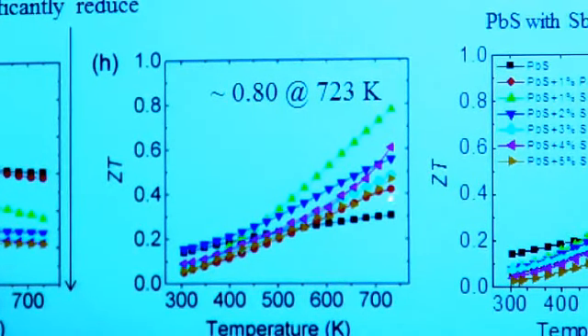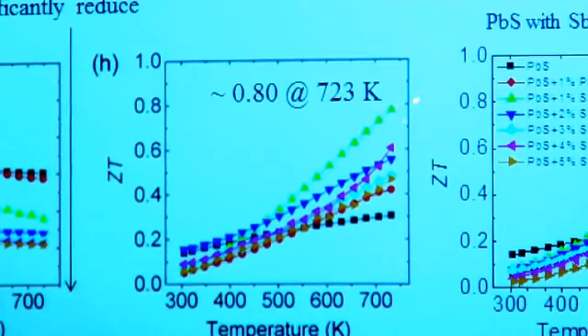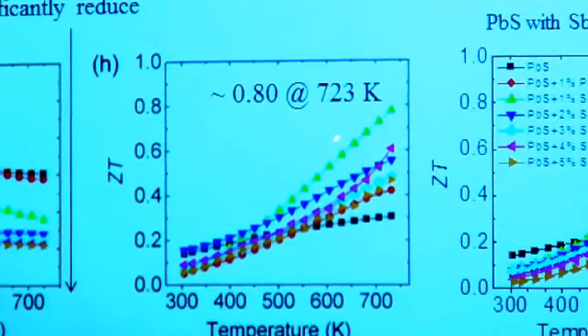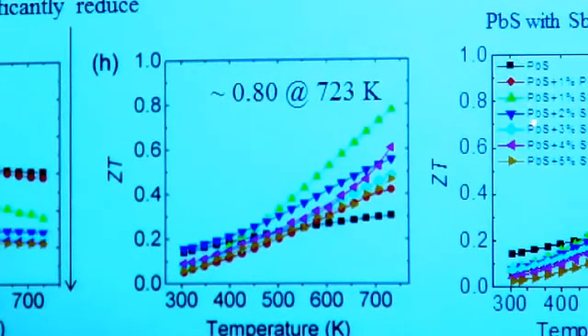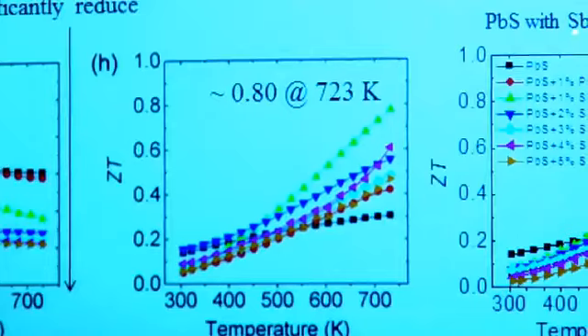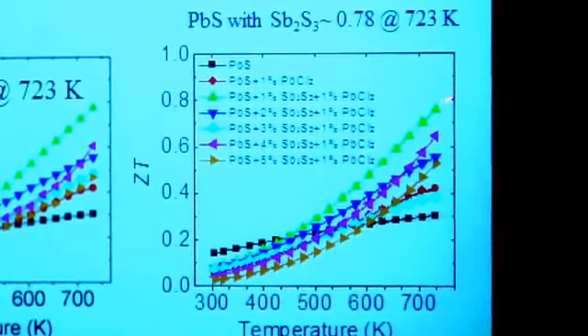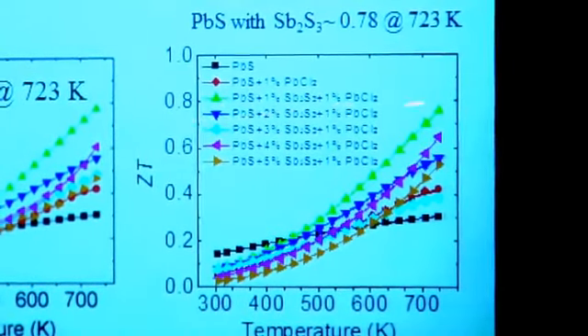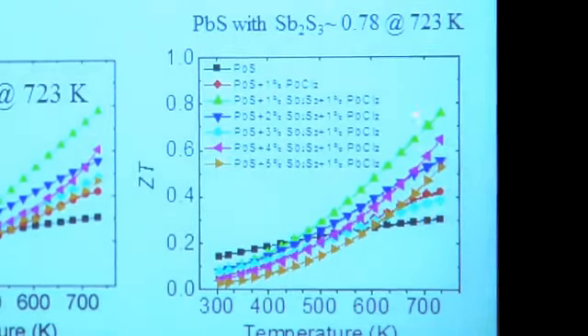Actually, we couldn't get 0.4, but it gets 0.4 at higher temperatures. Here's the samples. We have samples that are going to 0.8, and they keep rising with no sign of saturation. So we get 0.8 for this sample, for the antimony sample. This is the antimony. We get a similar number, about 0.8 as well. So this is a big jump in ZT for this system.